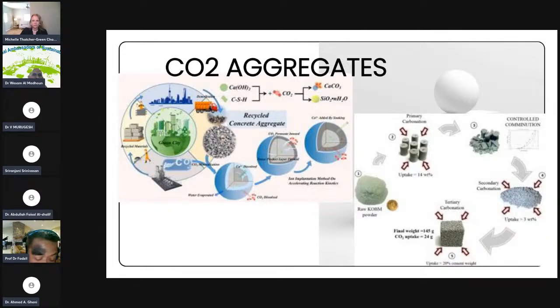In order to overcome this issue, research has been carried out by introducing CO2 to the recycled concrete aggregate. We successfully transformed the calcium hydroxide into calcium carbonate in the recycled concrete aggregate and improved the properties of the aggregate, such as the strength, the porosity, and the water absorption level.